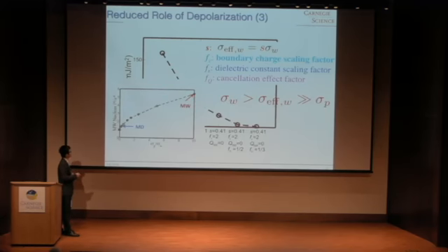In other words, the Wiener model, with an assumption of large depolarization energy, will give you a very large aspect ratio, but in the limit of smaller depolarization energy, which is consistent with MD observations, the aspect ratio of the nucleus is actually close to 1.